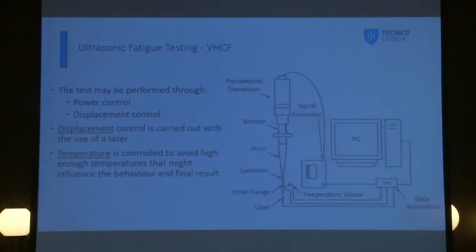We can perform this kind of test in two ways: in power control or displacement control. To do that, in the displacement control, we have here a laser to monitor the displacement. And of course, we have to take care about the temperature because if not, it might increase a lot and change the properties of the material.